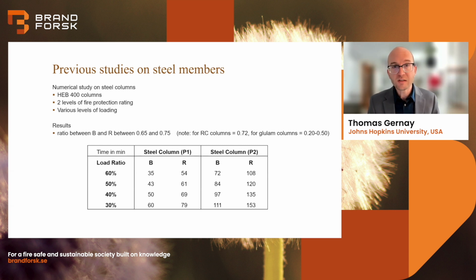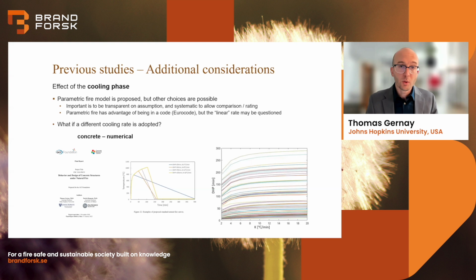There have been some studies on steel members and the effect of different levels of thermal protection on the steel members. And roughly what we found is that the ratio between the burnout resistance and the standard fire resistance is of the same order for the protected steel columns as it was for the reinforced concrete columns. The report also discusses additional considerations pertaining to the concept. For example, the effect of selecting different cooling phases.